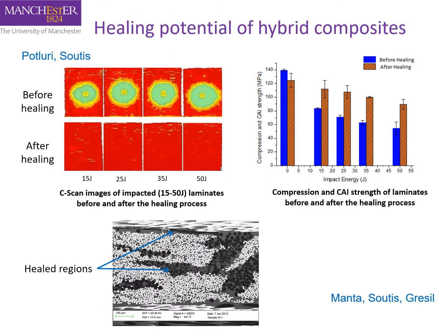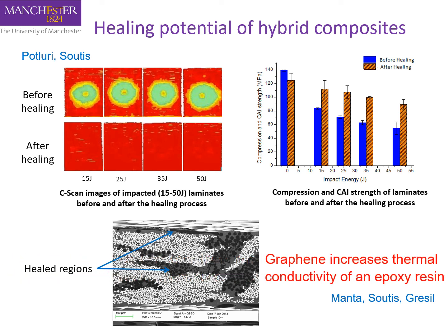We spoke of the healing potential of hybrid composites, where the polypropylene fibers upon heating melt, filling up the gaps and the delaminations and recovering compression after impact strength of the laminate. Graphene now increases the thermoconductivity of the epoxy resin, and this has the potential of speeding up that heating process.